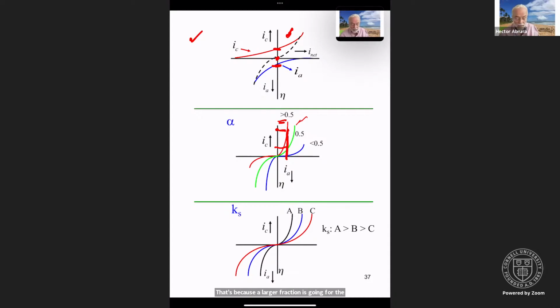On the other hand, if alpha is less than 0.5, that means you're favoring the oxidation reaction. And so you have the complete opposite. And so in the oxidation reaction at a given overpotential, then this current is clearly higher than this current at 0.5.